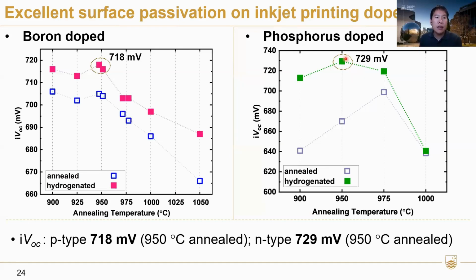A few things that are useful to note here is that the peak is quite flat around the optimum temperature of around 950. And the other thing, which is more interesting, I believe, is that the optimum temperature for both boron and phosphorus is around 950 degrees. Which is why we believe that we can actually co-anneal them, but we'll look into that in a bit more detail later.